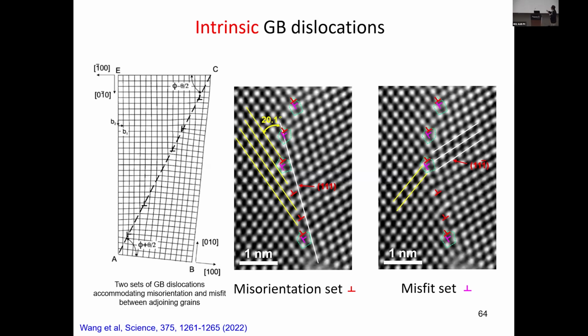So now we are able to clearly identify them, right? In the fundamentals of dislocation textbook, you have an extra half plane. That means you have one dislocation core here. And when you have this lattice mismatch, we also have this misfit dislocation. So they combine to form this pentagon structure unit.